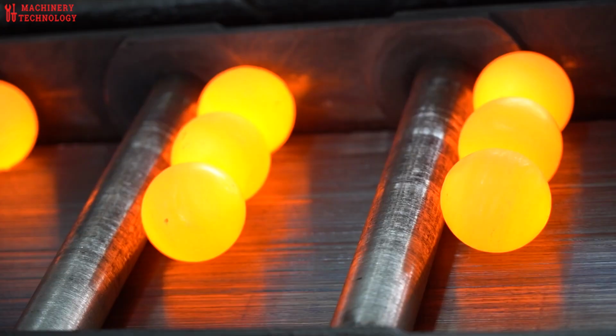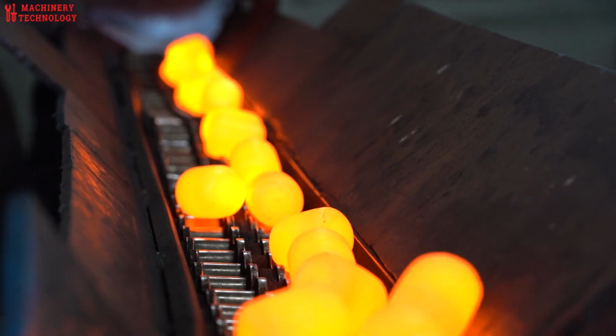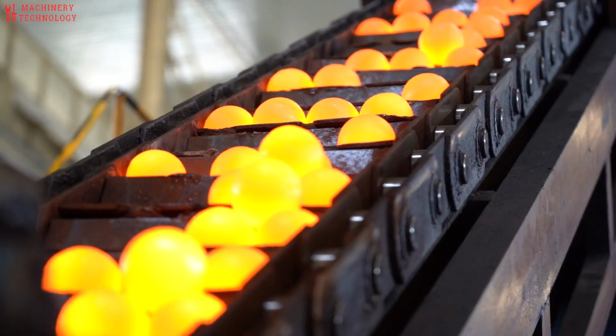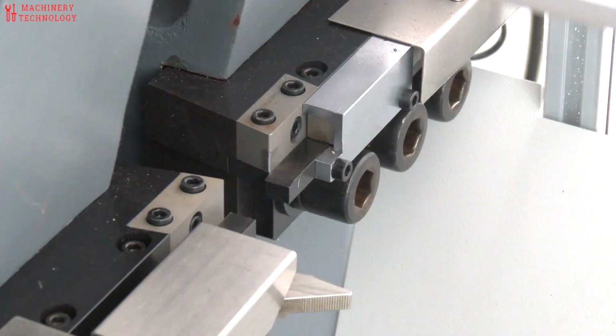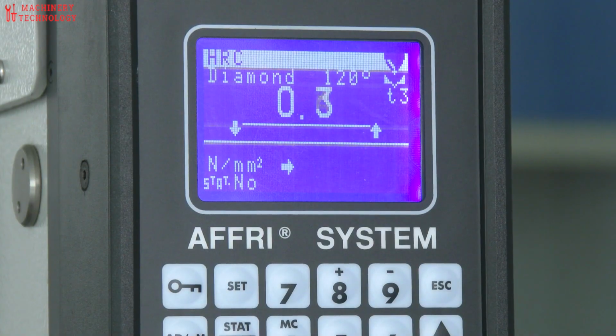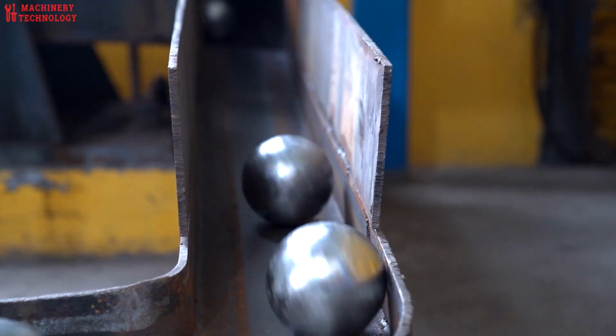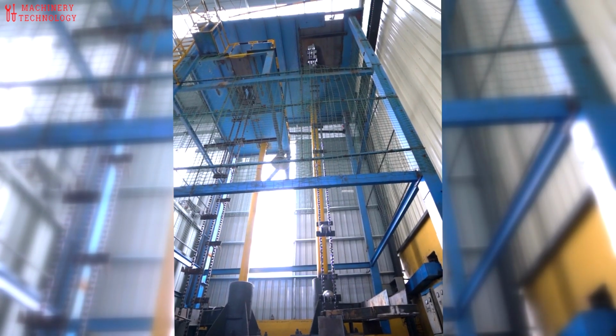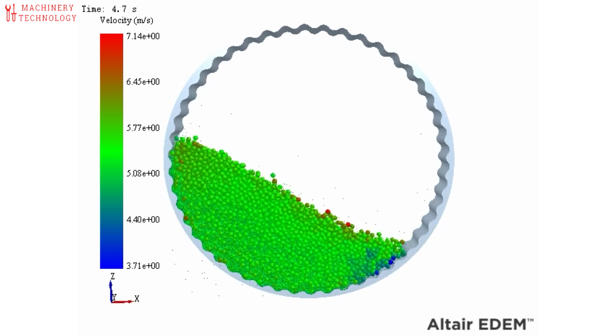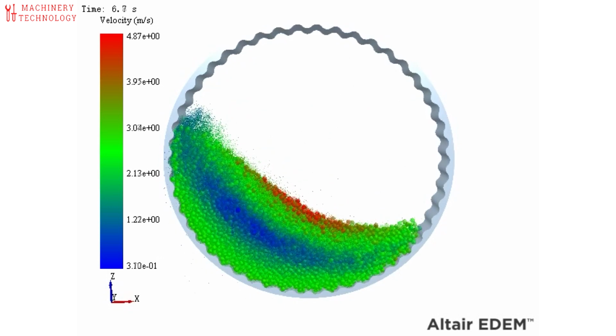The steel balls are reheated in a controlled atmosphere furnace to a critical temperature, austenitizing. They are then rapidly quenched in oil or water, a process that induces martensitic transformation, resulting in high hardness and wear resistance. To balance hardness with toughness, the balls are reheated to a lower temperature, typically 150 to 650 degrees, and allowed to cool slowly. This process alleviates internal stresses, reduces brittleness, and ensures the balls can withstand impact loads without fracturing.